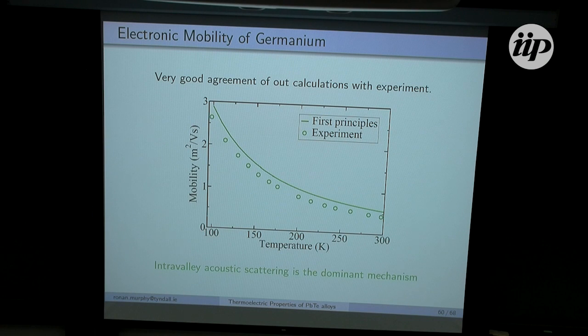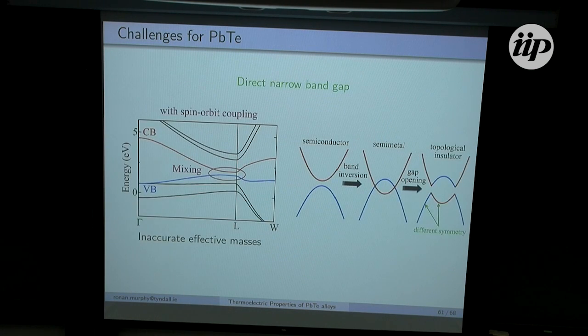Now, repeating this for lead telluride, we run into a few different issues. Lead telluride has a very narrow band gap at the L point, about 0.3 electron volts. So if we take the electronic band structure here and include spin-orbit coupling, we run into a problem. You can see here that the valence band and the conduction band are very close to each other, and there's mixing of the states and an inverted band gap.